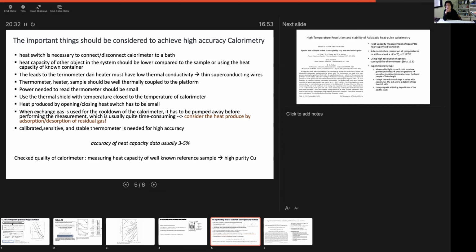That's why there are no conduction electrons which can carry heat inside the superconducting state. If you want to make a heat carrier, you have to break the superconducting state and break the Cooper pairs into conduction electrons. That's why the superconducting state is a very bad heat conductor. So that's why people use superconducting wire or superconducting material to make a heat switch or adiabatic space.